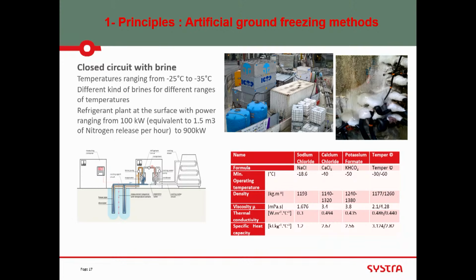If we use brine, we have a fridge, so this is a fridge unit. The fridge, in fact, decreases the temperature of the liquid. So we are not using sodium chloride because the temperature is only -18 before freezing. So this is salt water. We are using calcium chloride or Temper, which is a trademark, which goes to -40, which means that the temperature, when it goes out of the fridge, is at -40 or -35 usually. And this temperature at -45 goes into the pipes that we'll see in 2 minutes, goes down, goes up, goes to the next, goes up, and so on, and in fact decreases the temperature of this area where the pipes have been installed.